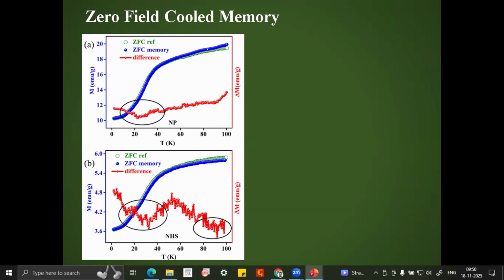During each halt, this time also, we allowed the system to relax for around 1 hour, and then we measured the magnetization of the system in the heating cycle. This is the blue curve, this is the memory curve. Now if we take the difference of the ZFC reference and ZFC memory curves, we get the red curve. This is the difference curve. Now if the difference curve shows a dip at those temperatures where the sample was allowed to relax, then we can say that the system exhibits zero field cool memory. Now we can see that for the nanoparticle, we have only a very weak memory dip at 20 Kelvin.